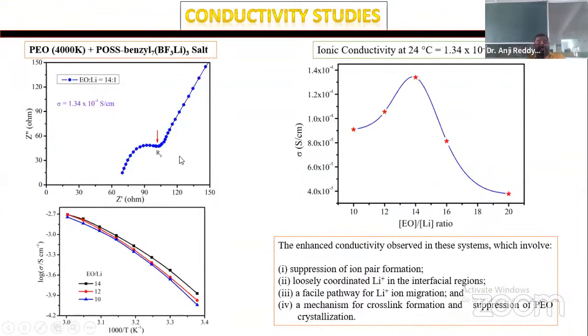If you observe the conductivity, this is only with the PEO and phos lithium salt. We have not added anything here. At room temperature itself, we achieve the order of 10 to the minus 4. The conductivity is very good. Even with different EO to Li ratios, we got maximum conductivity at the ratio of 14. At 24 degrees, the conductivity is good.